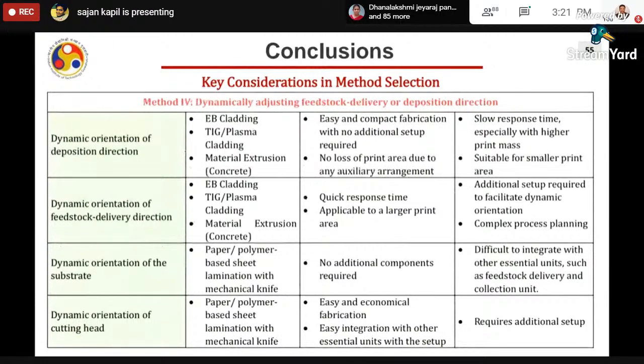Dynamically adjusting the feedstock is the easiest way to do that. Dynamically, you either change the orientation of the deposition vector by changing the direction of feedstock or substrate. It is slow in response. Additional setups are required. It is difficult to integrate with the system, and it always requires some additional setups. Response time is the major issue in this case. Like if I'm going with a very high speed, it takes some time to take the new position when we deposit on a nonlinear trajectory.